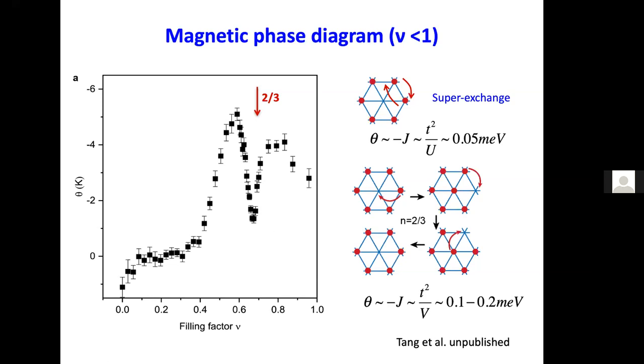Right. So then when you bring the screening layer close, you presumably get rid of the long range part of the Coulomb interaction and therefore destabilize this particular insulator. Yes. Right? So why does theta go back up? Is it that these processes are no longer canceling? So if you make V go away, the charges are no longer pinned.